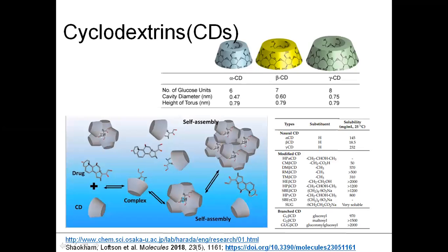The cyclodextrins comprise a family of three well-known major and several minor cyclic oligosaccharides. The three major cyclodextrins are crystalline, homogeneous, non-hygroscopic substances which are torus-like macrorings built up from glucopyranose units. In an aqueous solution, the slightly apolar cyclodextrin cavity is occupied by water molecules which are thermodynamically unfavored and therefore can be readily replaced by appropriate hydrophobic guest molecules. The stoichiometry of drug-cyclodextrin complexes is most frequently 1-to-1.